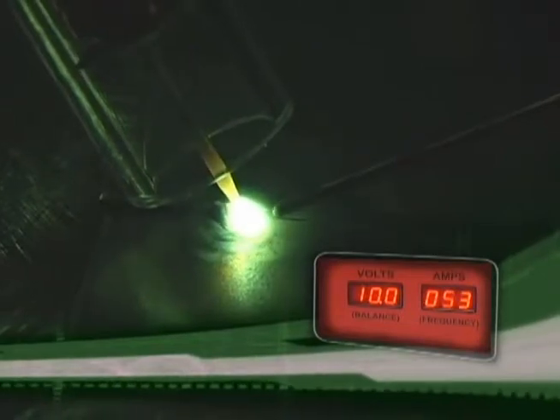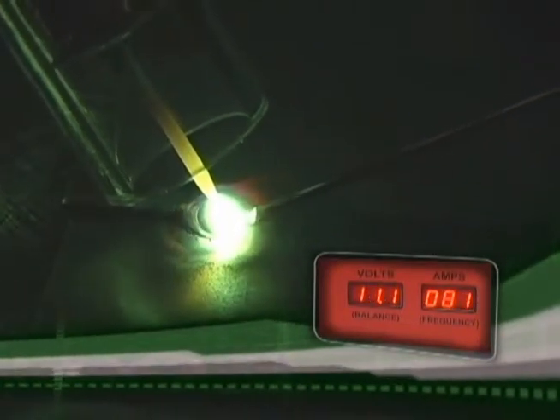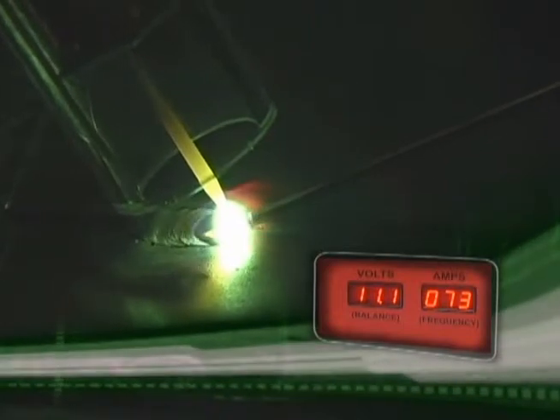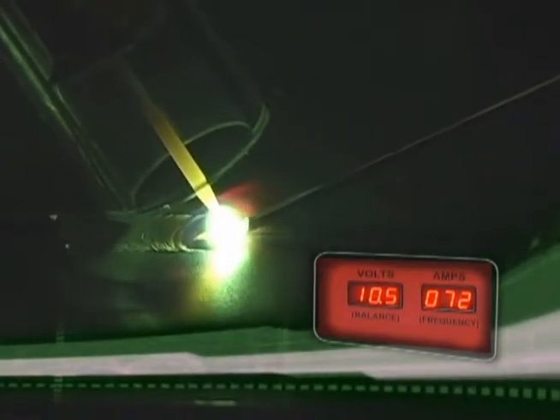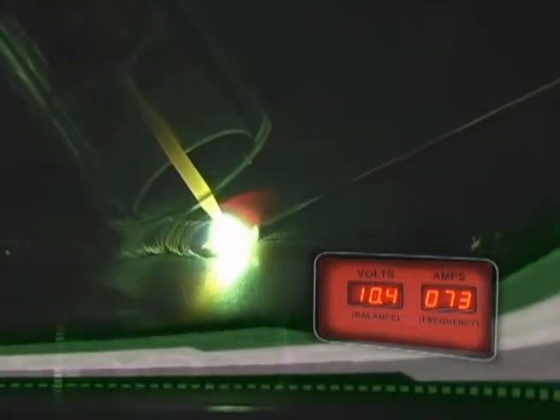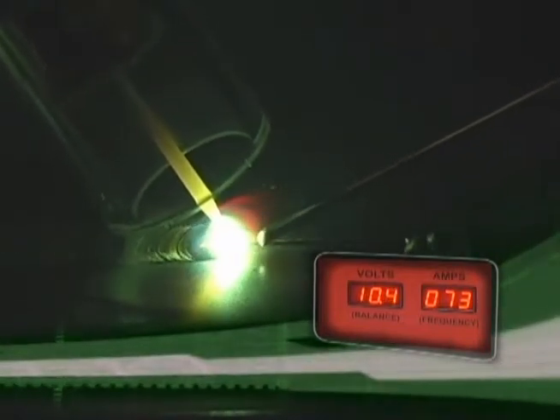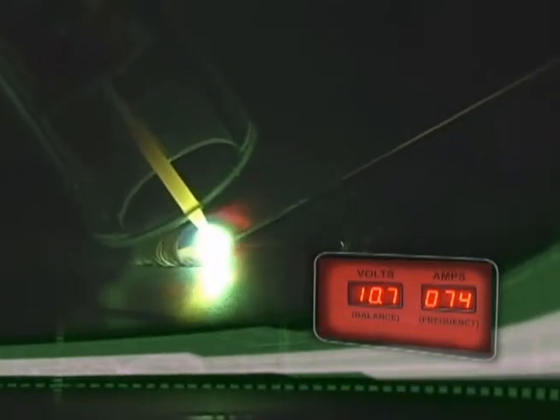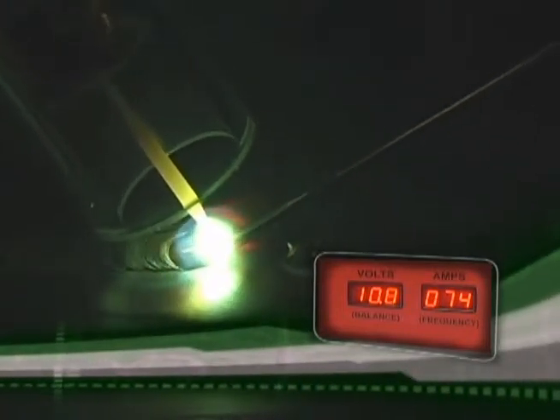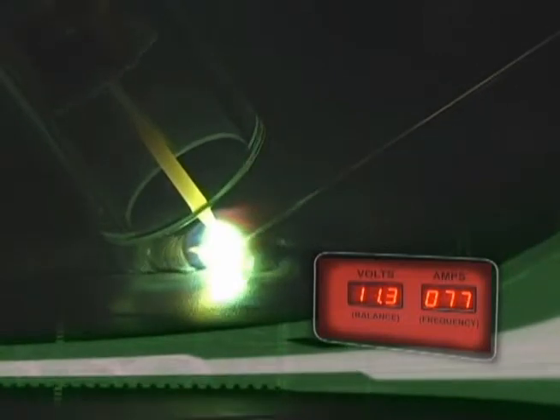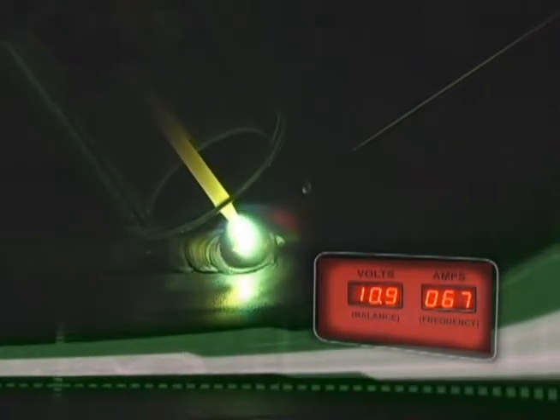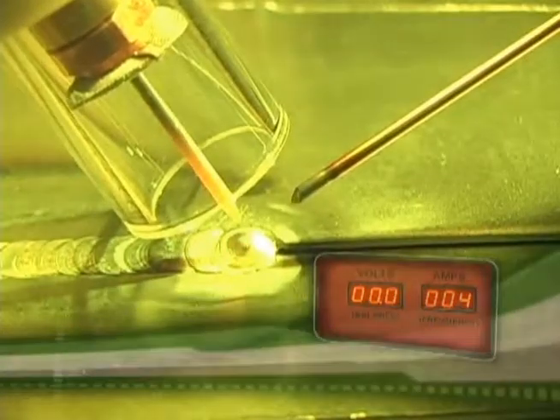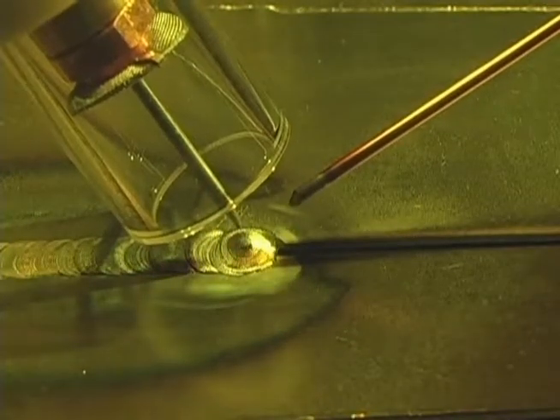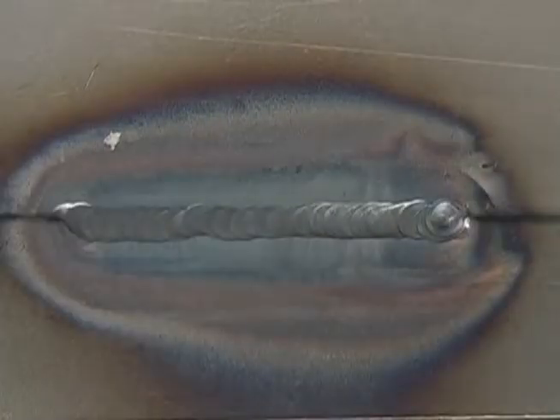Get a molten puddle started on the lower panel. Then dab the filler into the molten puddle and get the molten puddle to wick up into the top panel. If you apply too much heat to the upper panel or let the arc start and stay on the upper panel, the edge will just overheat and melt away. The finished weld is a nice consistent weld. You can see the heat affected zone is also consistent.